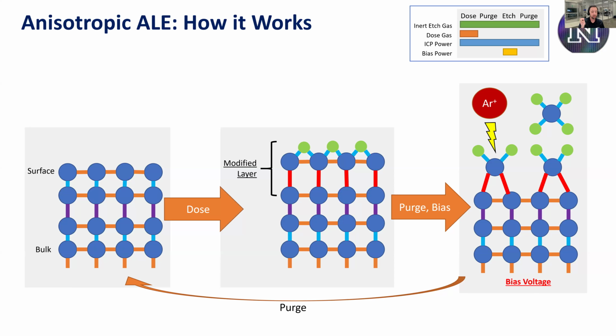If you look at the upper right, that's generally how these things work. You leave the inert etch gas flowing, you leave the ICP power on through all your dose, purge, etch, and second purge. You dose during the dose step, purge it out a little bit. You etch during the etch step, so you just have inert gas in there, and you turn on the bias, and that's how it works. Fairly straightforward in most cases.